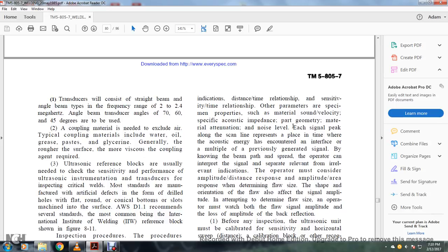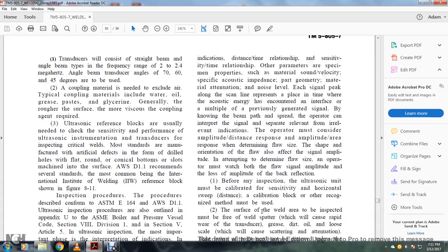Material attenuation and noise level matter. Each single peak along the scan line represents a place and time where the acoustic energy has encountered an interface, or a multiple of a previously generated signal. By knowing the beam path, the operator can interpret the signal and separate the relevant from the irrelevant indications. The operator must consider amplitude, distance response, and amplitude area response for determining the flaw size, shape, and orientation of the flaw, also affect the signal amplitude. Attempting to determine the flaw size, the operator must watch both the flaw signal amplitude and the loss of amplitude of the back reflection.